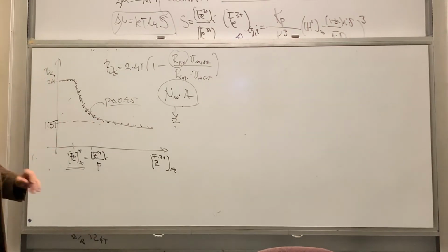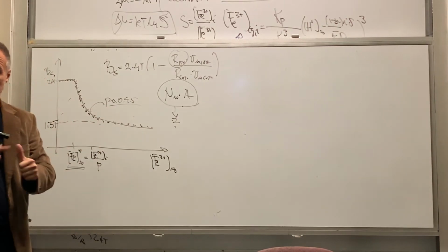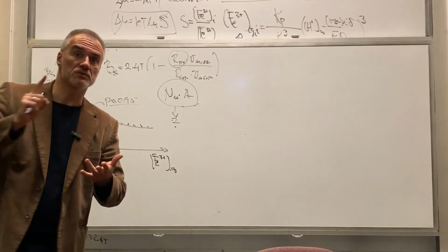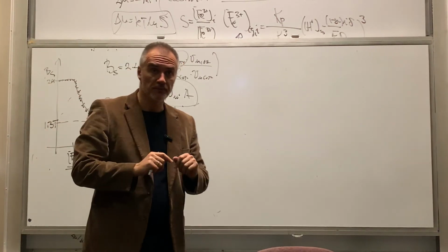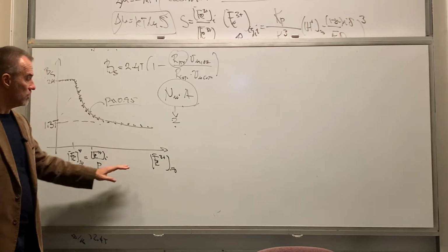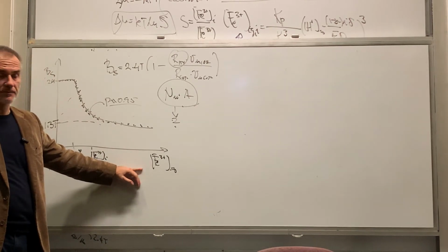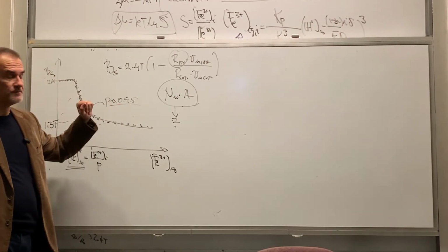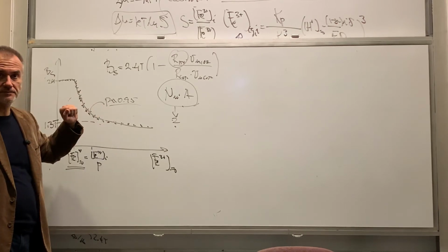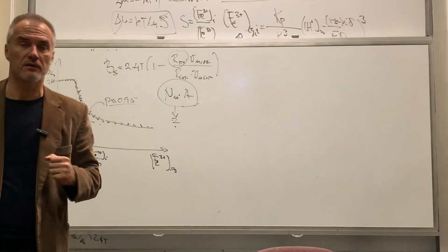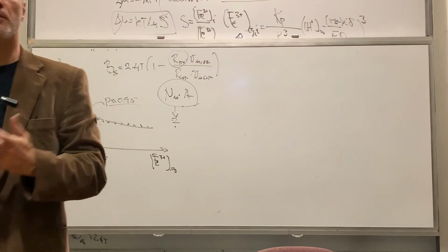That's very important. So now you have your process for the current density, solution design, pH, whatever we discussed. You have your data where you controllably entered iron 3 in the solution. You fit your model to the data, and now you have your P. Guess what you can do now? Now you can simulate your problems.